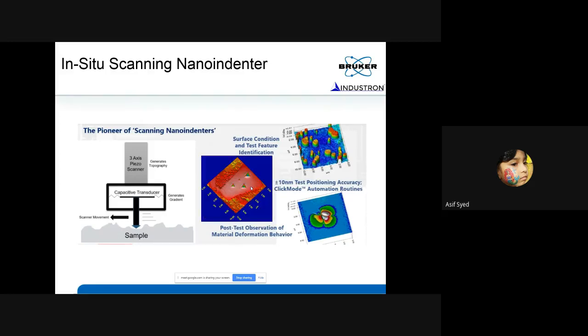Okay? Now this is another image where you can see a morphology of the surface, which is a two-phase ceramic material, and you can see the ceramic part as well as the matrix, which is an epoxy part. And you can also see there are triangular indents being placed, and these are the locations that you can choose to do the indents. So this is the SPM image that normally you get.